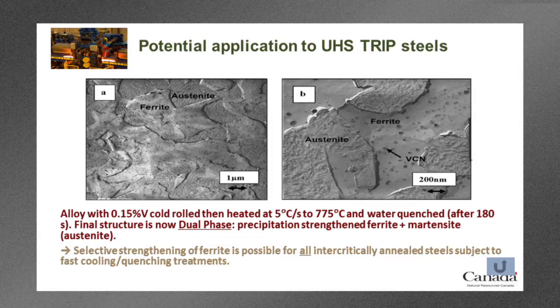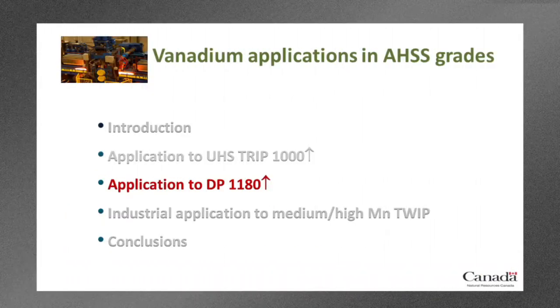And again, you can see on this right-hand diagram, the ferrite in that case is very strongly strengthened by a high density of vanadium carbonitride precipitates, whereas the austenite, which has now become martensite after the quenching, has very few precipitates in it. So this type of strengthening behavior, the selective strengthening of ferrite, also works in dual-phase steels. And there's no reason at all why it shouldn't work with other steels, maybe third-generation steels, for example, if they are intercritically annealed and subject to fast cooling and quenching treatments. Okay, so that's all for this section.